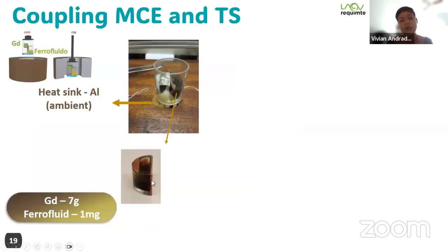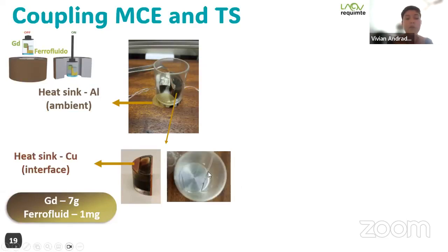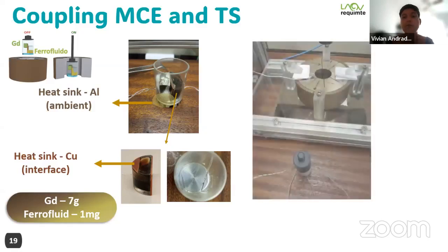On one side, we have the copper to be in contact with the gadolinium, that's our magnetocaloric material, and a small heatsink of copper to be connected at the interface with the aluminum heatsink. We also coupled a thermocouple to monitor the heat transfer at this part.